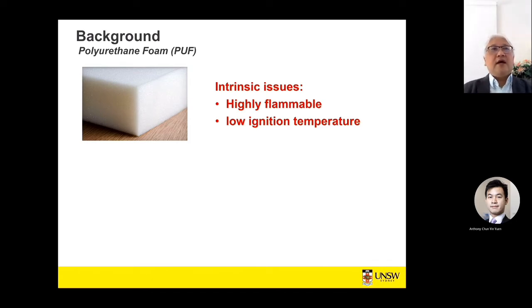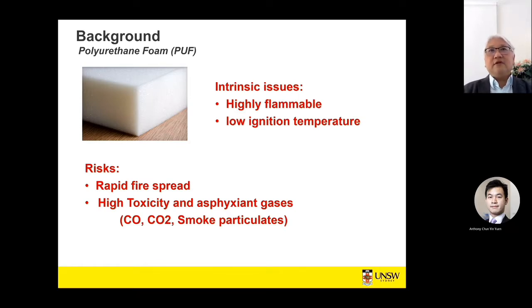Basically, it's highly flammable, and it ignites at a very low temperature. You're talking about roughly between 180 degrees to 200 degrees, and it will ignite. So the risk is that if you have a sufficient amount of these materials present in your homes or office spaces, and one of them burns, you could cause a rapid fire spread. And because of the rapid fire spread, it could result in a lot of gases being emitted in the form of carbon monoxide. And we do know as well that polyurethane does emit hydrogen cyanide in some quantities as well.